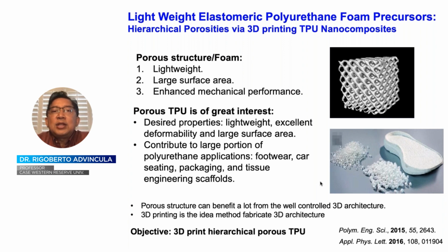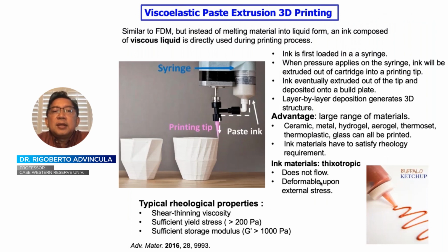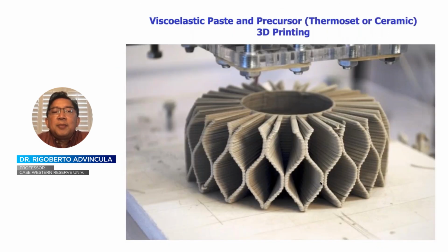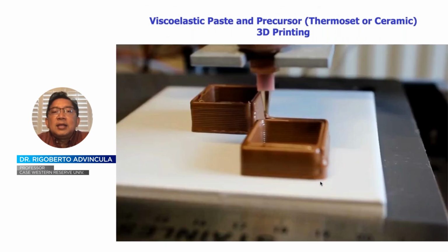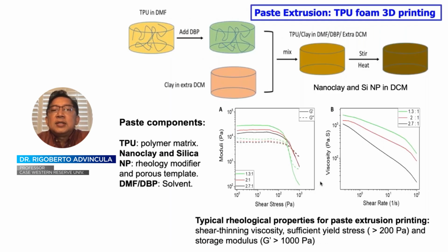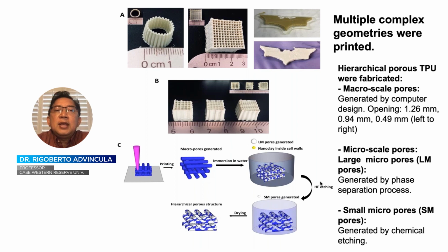So it's actually interesting that with 3D printing, we can make our own 4D response or stimuli response by using a thermoplastic polyurethane that we can then deposit, let's say, with FDM or viscous solution printing to produce a material. So in our case, we actually use VSP, which I sometimes call a ketchup printer, or a printer for cement or chocolate. And this relies on the extrusion of a viscous material that, again, with CNC movement in the 3D printer, allows you to deposit at room temperature with the right shear thinning and thixotropic behavior. This will give you an elastomeric or thermoset elastomeric material. So actually, we have reported this in previous talks and papers, where we took the thermoplastic polyurethane, loaded it up with nanoclay, and then used this formulation to do 3D printing of objects as shown here.